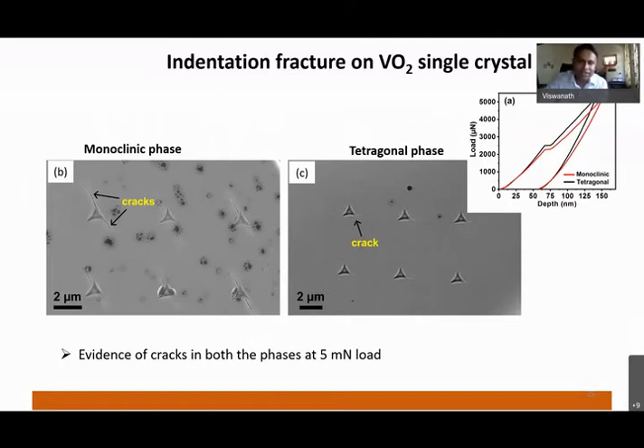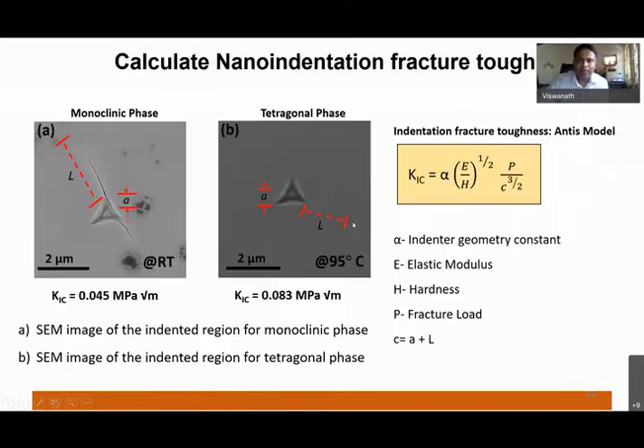Then we checked the literature, and there is no single paper that reports a fracture toughness value of vanadium dioxide. Then we thought, why not measure the fracture toughness in single crystal by doing indentation in the monoclinic phase at room temperature, and the tetragonal phase at around 90 degrees Celsius. The SEM images you are seeing here, one indented at room temperature, one indented at high temperature, but imaged at room temperature. By taking the crack lengths and so on, we are able to get the fracture toughness. We use the ANTIS model based on the c/a ratio.